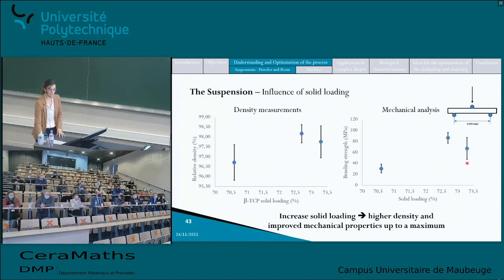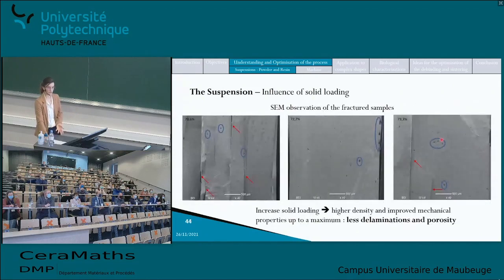And this could be explained by the fact that the suspension prepared with the highest amount of powder has a very high viscosity, so that can cause defects appearing during the printing process. I did some SEM observation to pursue the experiments, and here it appears that it's consistent with the results that were observed during the density measurement and the mechanical analysis.